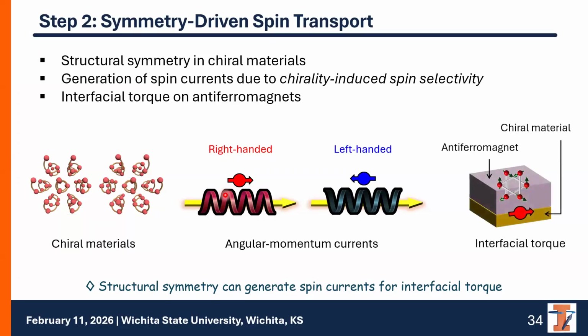And this generated spin current can exert a spin torque on the adjacent antiferromagnetic layer. Thereby, finally, we can excite the magnetic multipole spin dynamics in antiferromagnetic materials. So from this, we can obtain a symmetry-governed handle to drive the multipole excitations in antiferromagnets.